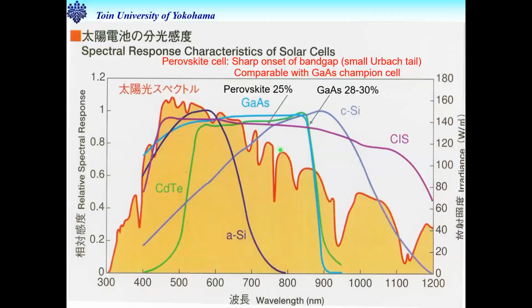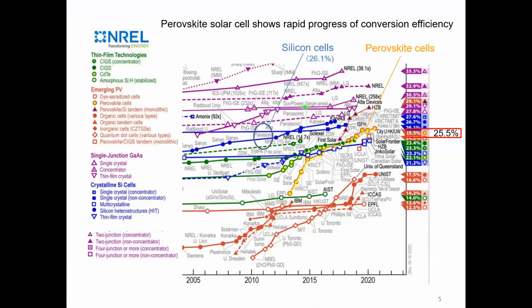When you see the spectral sensitivity of the perovskite solar cell, its shape is similar to gallium arsenide, a champion semiconductor achieving the highest efficiency with a single semiconductor, 28-30%. Perovskite is an excellent semiconductor with very strong absorption, which extends to 800 nanometers. Gallium arsenide can absorb light up to 900 nanometers. The gap is 100 nanometers, but both cells are able to harvest all visible light. Silicon can respond up to the infrared region, but its light absorption power is much less than perovskite and gallium arsenide.